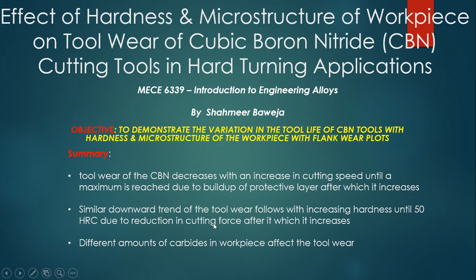After that, the tool wear increases for hardness above 50. Besides the hardness and the cutting speed, the most important parameter that affects the tool wear is the different amount of carbide in the workpiece. All of these points I'm going to elaborate more with the figures on the next slide.